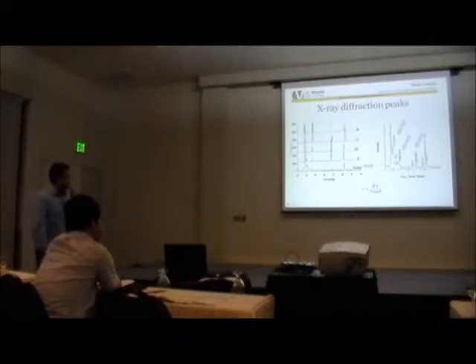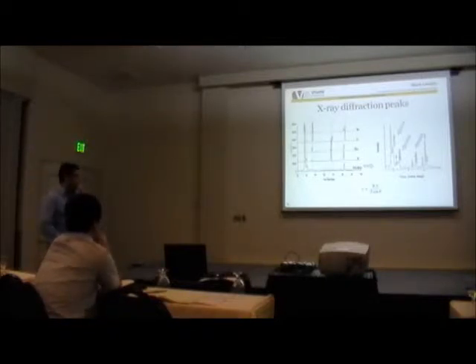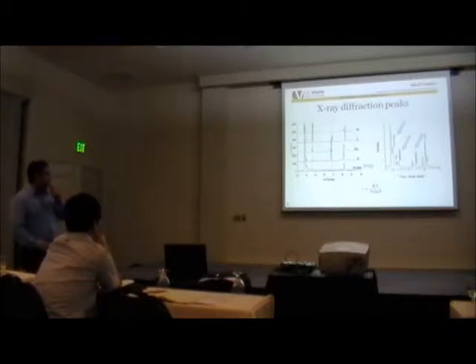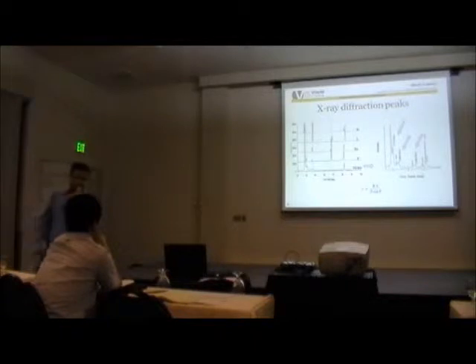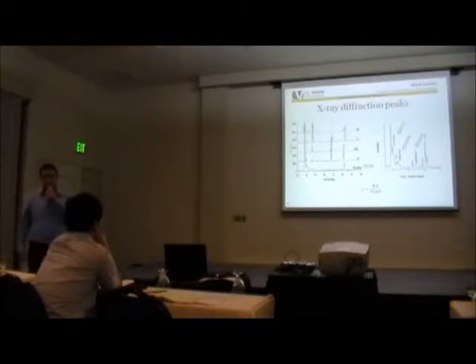Typical X-ray diffractions were done for two main purposes. First, I had to calculate the grain size by using the Scherrer equation. And the second was to find the correspondence between this electroplated thin film to make sure if I have an alloy and it's not just pure platinum or something else.